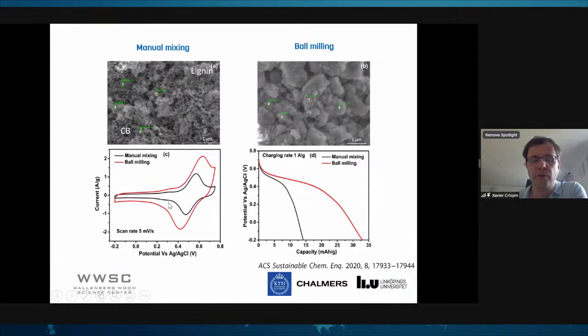So the result is the following: the black curve in the cyclic voltammogram. You see you have a capacitive behavior due to the carbon, and then you have the peak due to the lignin here. Now the peak is not great enough, so if you instead use a ball milling machine and really mash and crush those carbon black into tiny particles, and after you look at the SEM, you cannot recognize, basically, even when you do atomic elemental analysis, you cannot see any phase of any specific carbon or lignin. Everything is mixed at a very, very tiny scale, basically in a nanoscale.